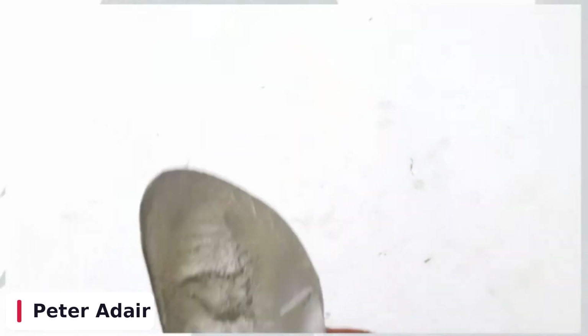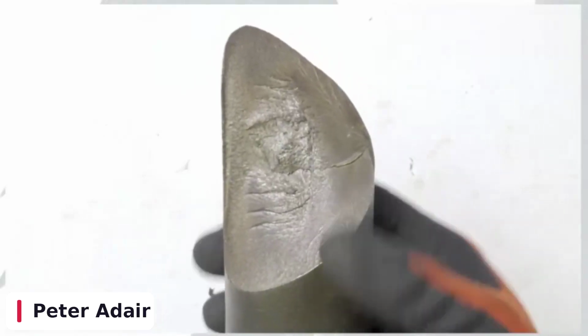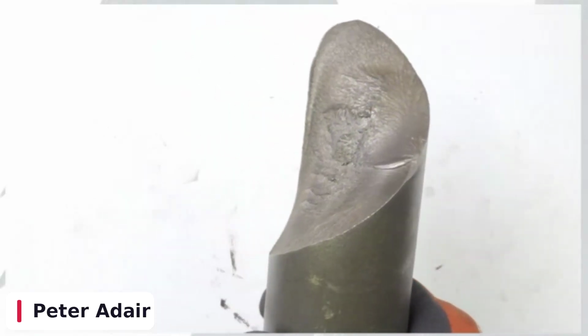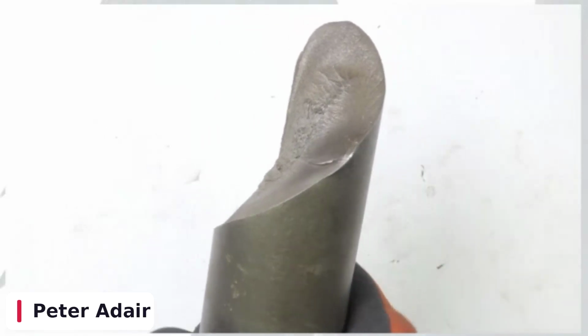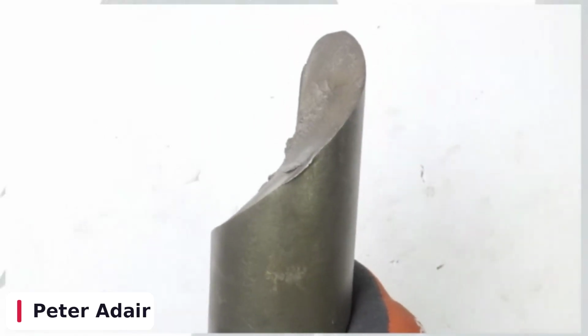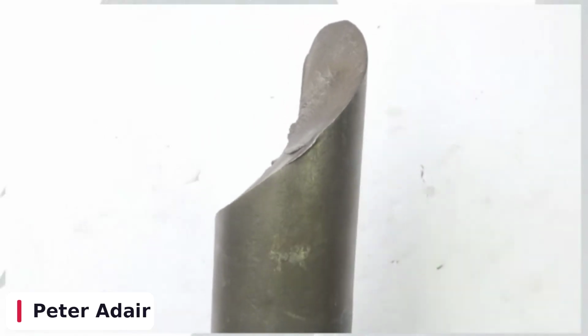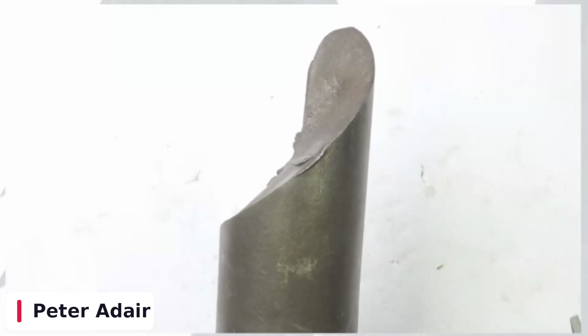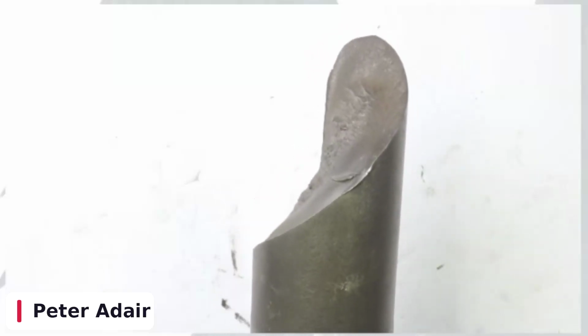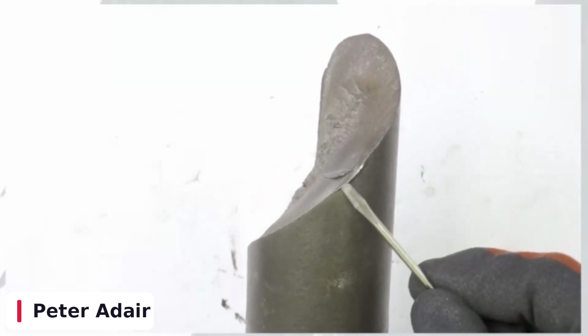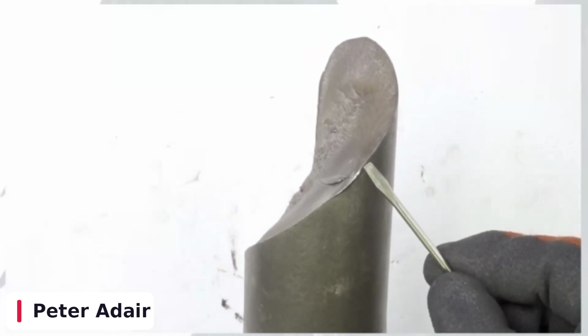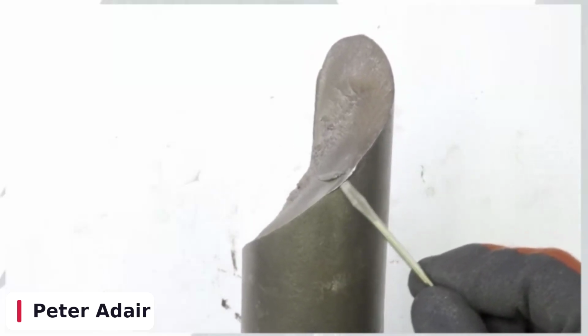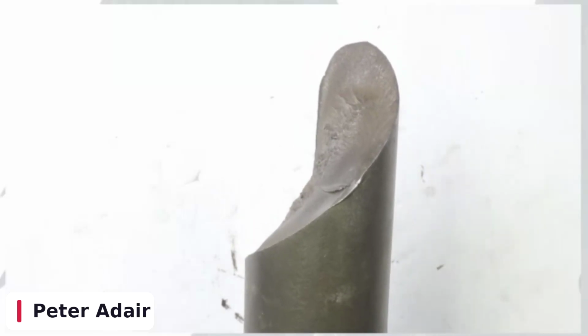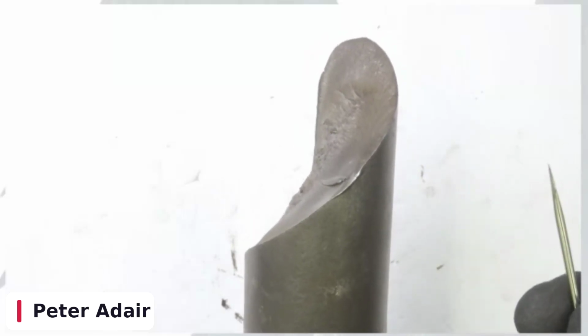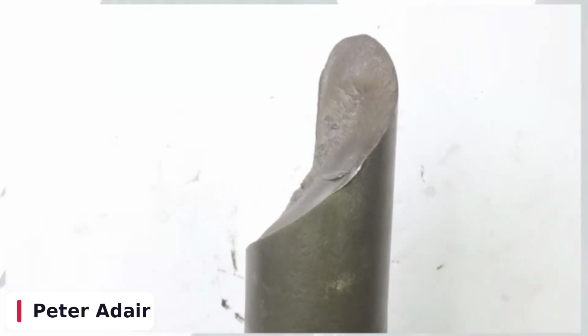What I am going to look at is I'm going to rotate around to the origin, nice and slow, and we can see something there. Heck, this camera is so amazing that you guys can actually see the issue in the shaft. How many of you guys have dropped an axle shaft on the floor or slammed it on the side of your bench and put a nick in it or put a dent in it? And if you have, that's going to be where that shaft breaks.